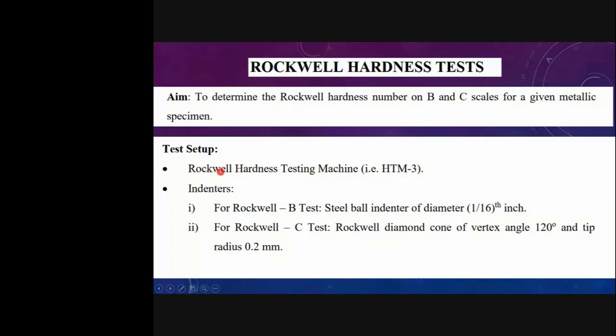The test setup includes the Rockwell hardness testing machine, the very important one, and the indenters. These are used to make some marking on the material. We have two scales, as I told. For the B scale, we use a steel ball indenter of diameter 1/16 inch. This is for the soft material, and the Rockwell C is for the hard material, and for that we use the Rockwell diamond cone of vertex angle 120 degrees and tip radius of 0.2 mm. You know the diamond is a very hard material, so you need diamond for testing the hardness of hard materials.